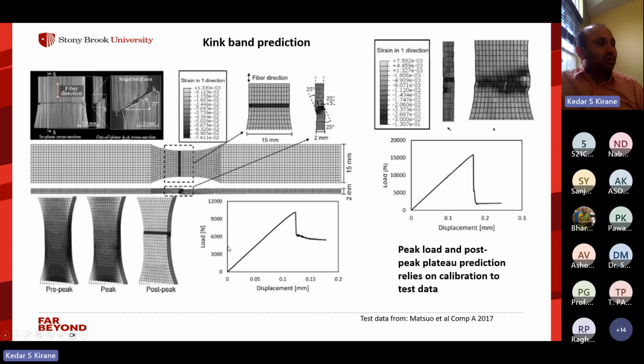And you can see that the load displacement plot is also consistent with experimental observations: linear, reaching a peak, sudden drop, and then the load remains non-zero for a long time. This is out of plane kinking. We didn't have any experimental data on the same material for in-plane kinking, but we kind of enforced in-plane kinking to happen, and we can capture that also in case it happens.